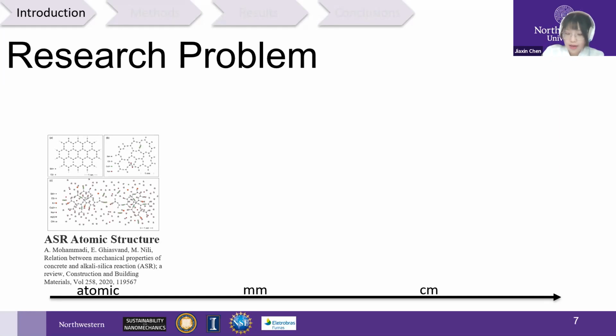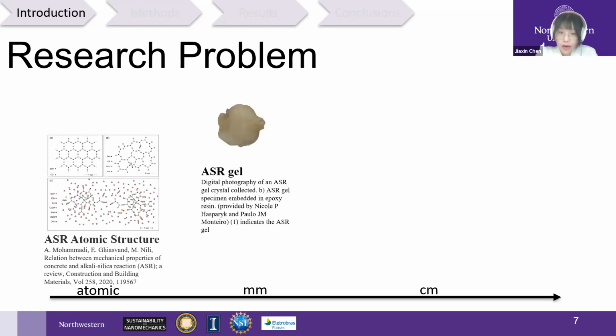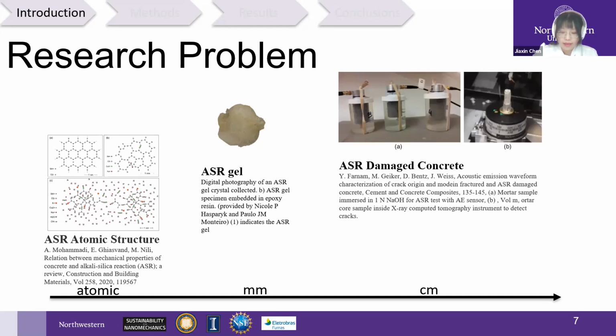So what did we do to have a better understanding of the alkali-silica reaction gel? From the atomic scale, definitely we have experts in this atomic scale in our department. Then ASR structure to microscale level, which is where our research fits, our ASR gel, and then to the centimeter level of ASR damaged concrete. At higher levels, such as macro scale levels, we have mathematical models to predict ASR damage and simulation models developed at our department and Northwestern University CEE. We mainly focus on problems at the millimeter level in our group. Hopefully, we can provide some understanding of our ASR gel. In addition, the fracture behavior of ASR gel is so important to fully describe concrete deterioration and cracking due to the ASR reaction.